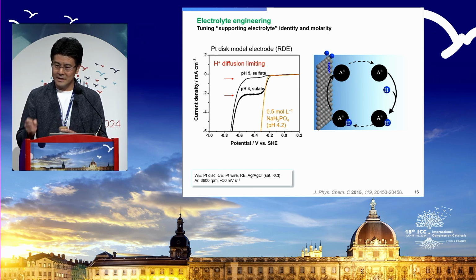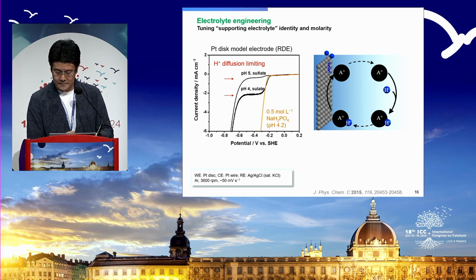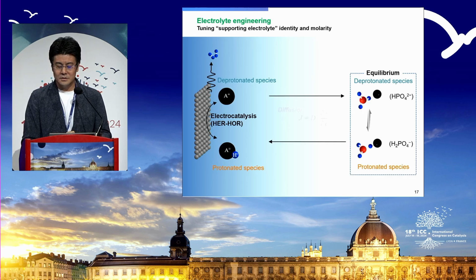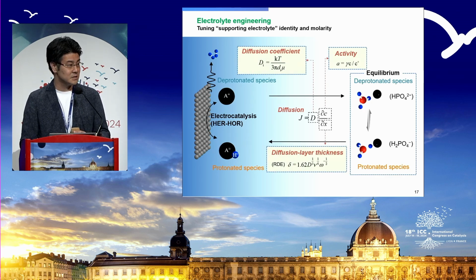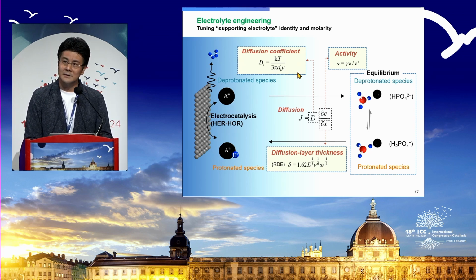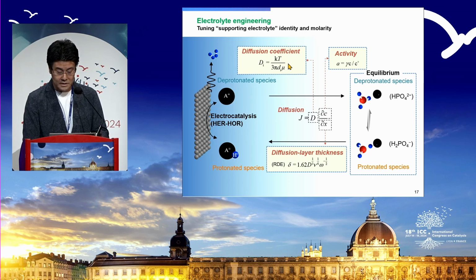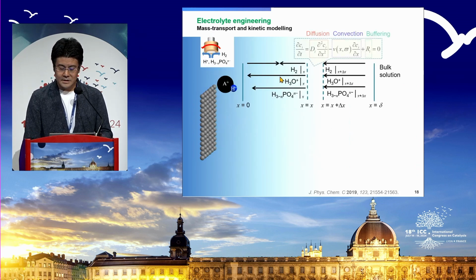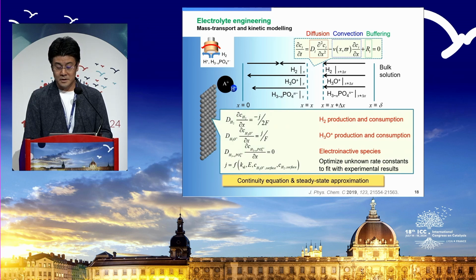Platinum is so good that once a proton comes, it picks it up to generate hydrogen. So platinum is waiting for the proton to come. Then we use a typical engineering approach, the steady-state approximation. We can also divide into the properties. Here, one of the most important factors is the viscosity of the electrolyte, which has nothing to do with electrode materials. This mu is the viscosity. So you can solve it for the steady-state approximation using this diffusion, convection, and buffering action.